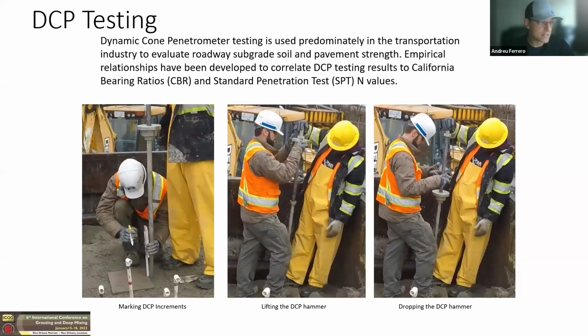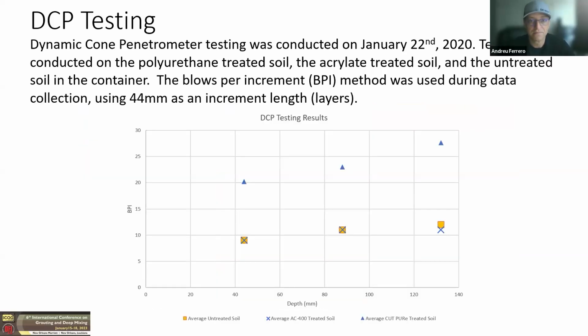So we did a series of dynamic cone penetrometer testing on the treated and untreated soils. DCP testing is used to determine California bearing ratios and verify standard penetration test values. These are the results from the DCPT testing. As you can see, the orange squares are the untreated soil. The blue triangles are the polyurethane treated soil, and then the blue X's are the acrylate treated soil.